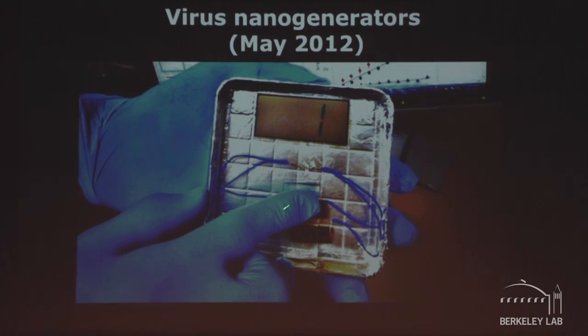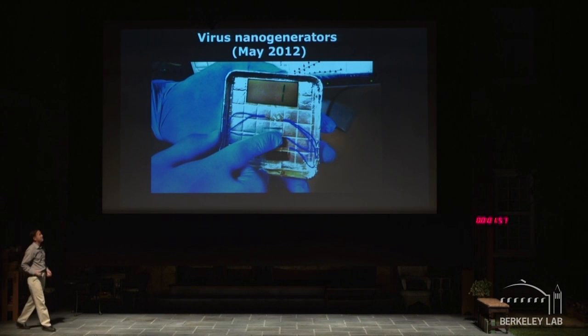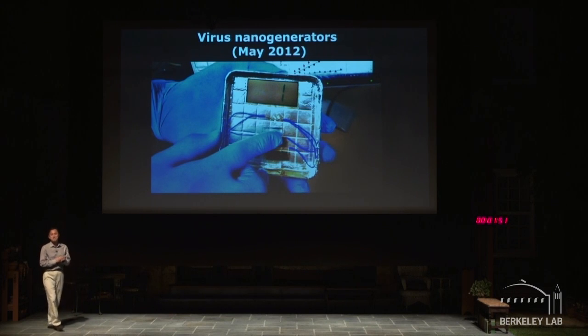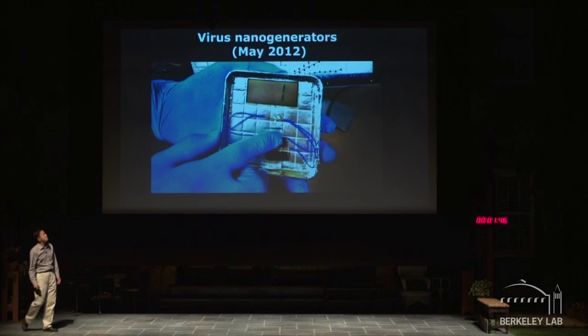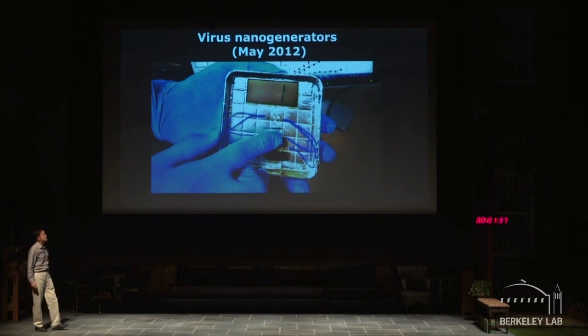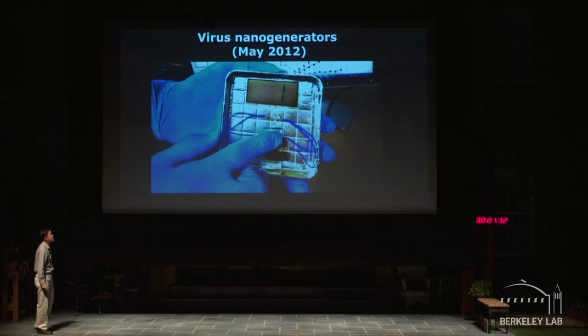Here is a virus film connected to a liquid crystal display — we press it and power the device to show the number one. That was a very exciting Eureka moment. In May 2012 we produced a very small current of 5 nanoamperes at around 300 millivolts. Over the last two years, we worked hard to engineer these viruses and improve the physical structure of the devices, improving performance more than 20 times.